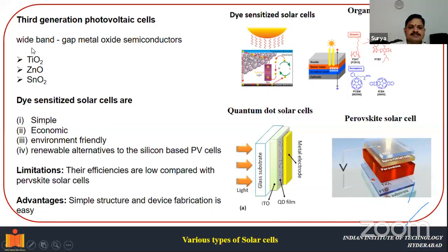So in the third generation solar cells, we basically use wide band gap metal oxide semiconductors, like titanium dioxide, zinc oxide, and tin oxide. And these dye sensitized solar cells have advantages in comparison with other solar cells because they are very simple, economic, environmentally friendly, and renewable alternatives to silicon based photovoltaic solar cells. Now the limitation is that the efficiencies are very low compared with perovskite solar cells, but still there is a lot of scope to improve the efficiency of these dye sensitized solar cells.